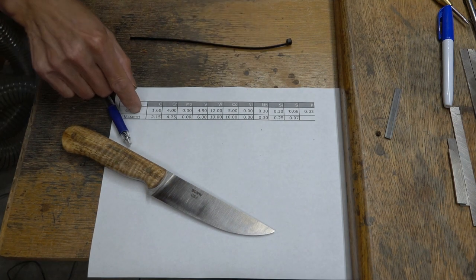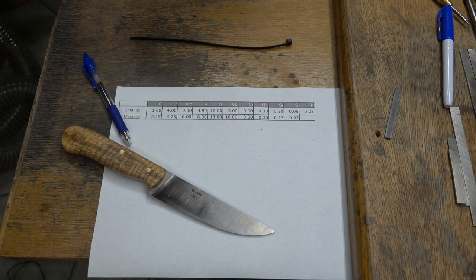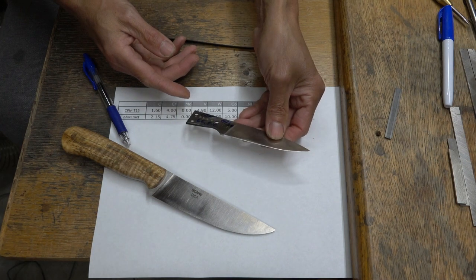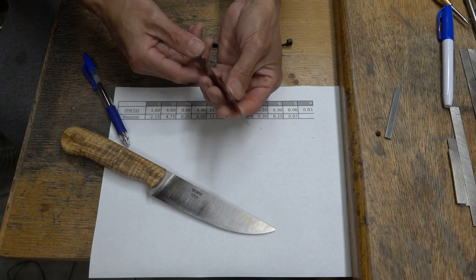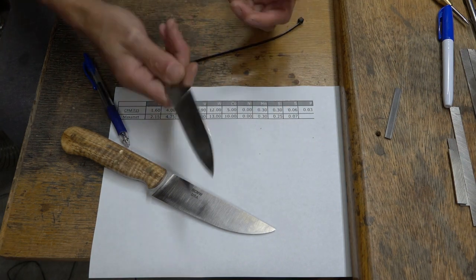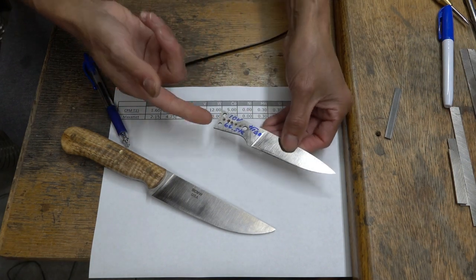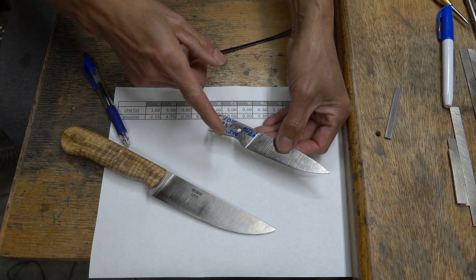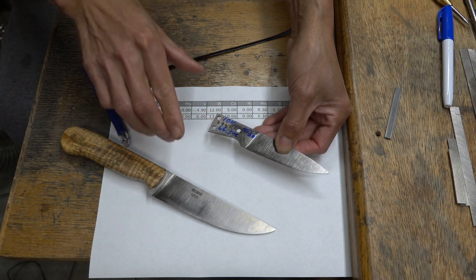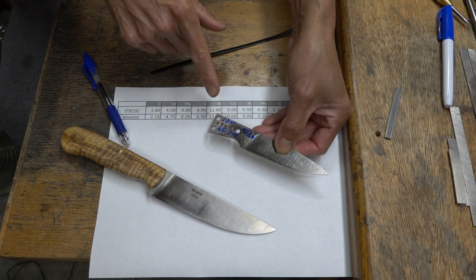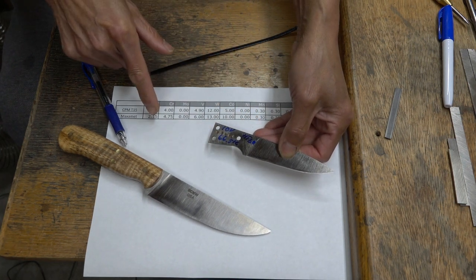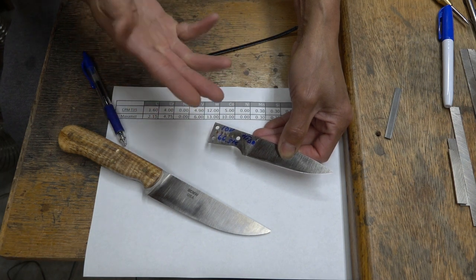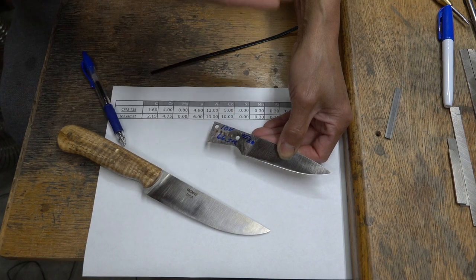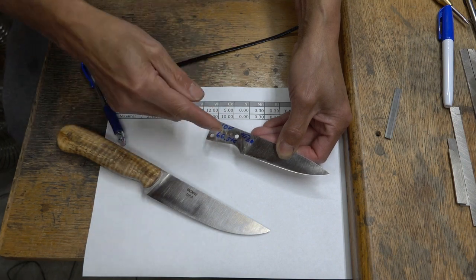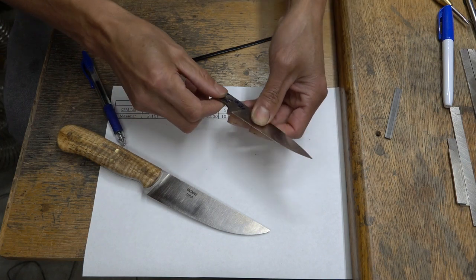But for example, like this 10V at 66.5 Rockwell, this will deform if I smack it with a nail or cut it with something, rather than chip, because it's capable of going to like 69 Rockwell. But I lower it enough so that the matrix is lower. The matrix is going to be down for this higher, like 9 percent vanadium here. I want the matrix probably at 64 or 65. And the carbide, you've got to add particle strengthening to strengthen it up, so the matrix can hang on to the carbide effectively.